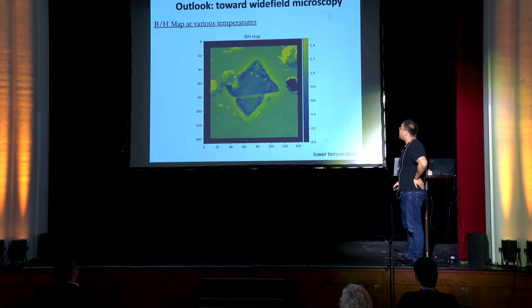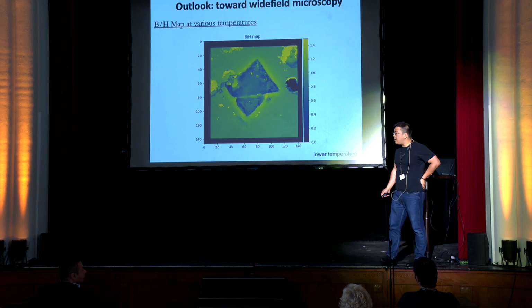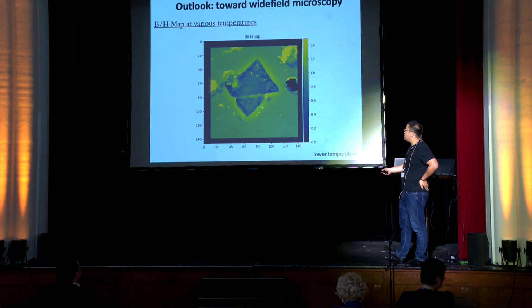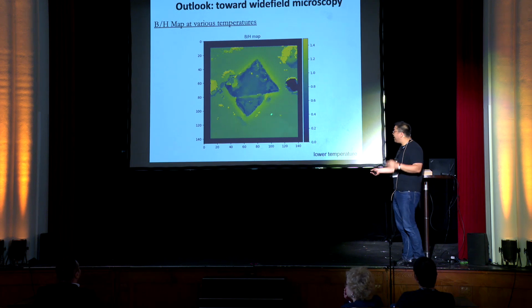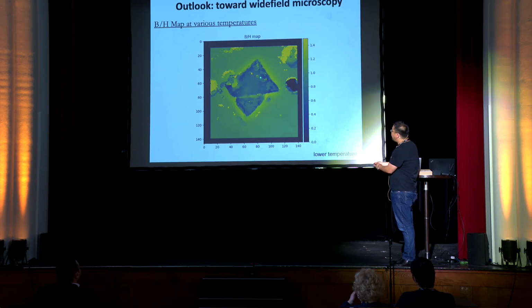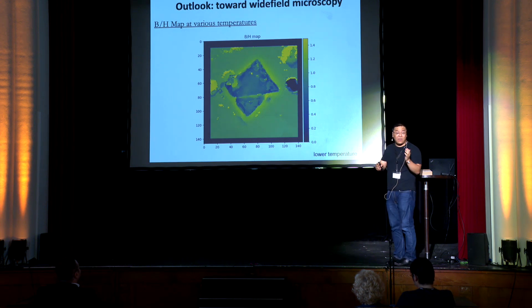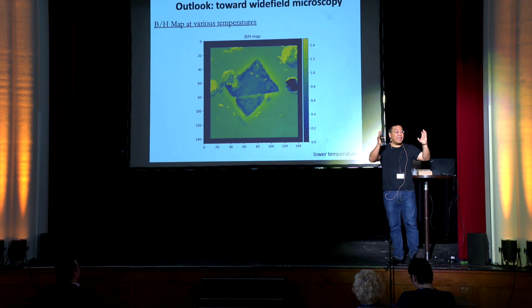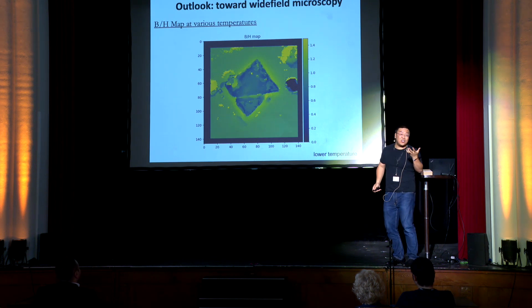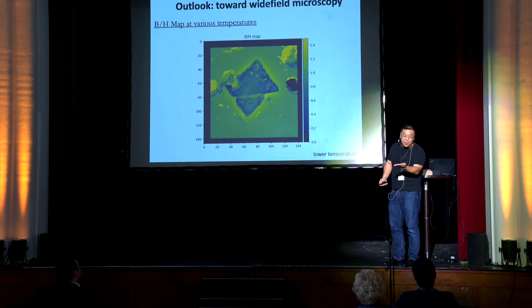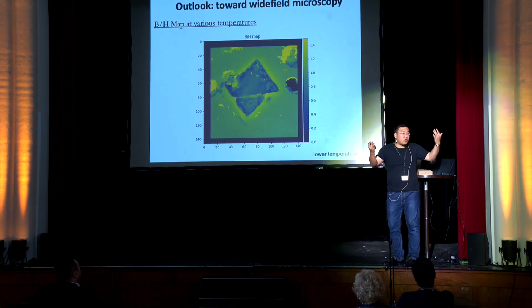But if you lower the temperature to just below the transition temperature, you start to see something kind of, in my opinion, quite beautiful emerge. So you see that for NV centers that are above the sample, there is a suppression of the magnetic field relative to the applied magnetic field. But the other cool thing is that for NVs that are on the edge of the sample, you see an enhancement of the magnetic field, exactly coming from the fact that the number of magnetic field lines has to be conserved. And there's just a super cool feature, not an important feature, but if you look at the sample and you look at transport, you could never say something about there being a break in the sample or any structural infidelity in the sample.